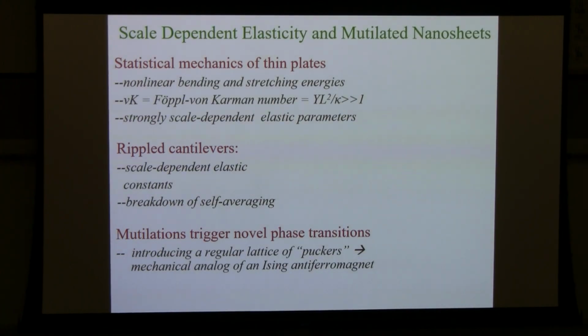This thin plate theory has in it a dimensionless number. This is the Young's modulus. This is the size of the sample squared. This is a bending energy, a bending so-called elastic constant. And this dimensionless thing tells you how nonlinear the problem is. When I crumpled this piece of paper, I think you won't be surprised to learn that's quite a nonlinear thing. The amount of the nonlinearity, the analog, if you like, of the fine structure constant, which would be an expansion parameter for quantum electrodynamics, is something called the Foeppl-von Karman number.